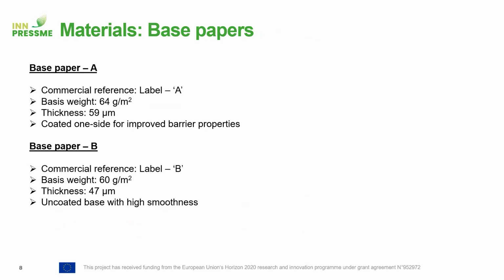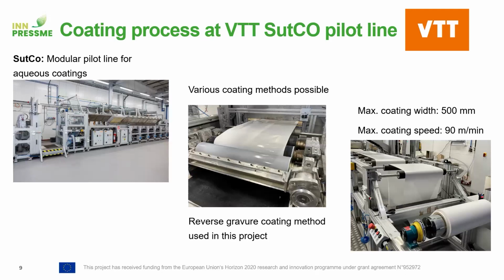So these three materials were then coated on two different base papers, different grades with slightly different properties, but they're labeled as base paper A and base paper B in the results. The coating process to apply these layers was done at the VTT SutCo pilot line. It is a very modular pilot line where we can apply these aqueous coatings.